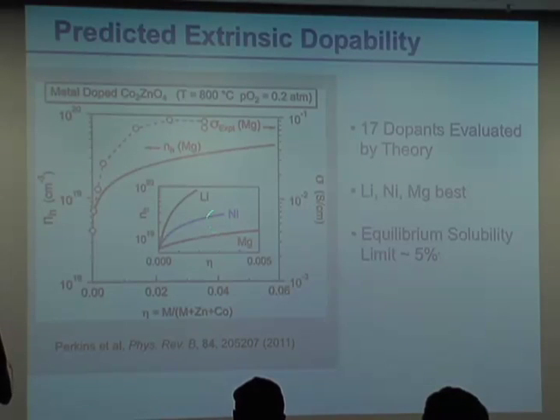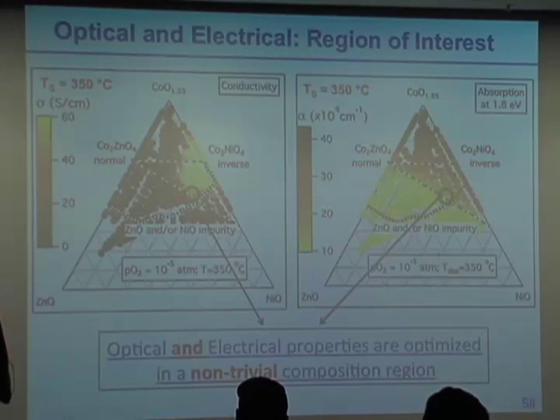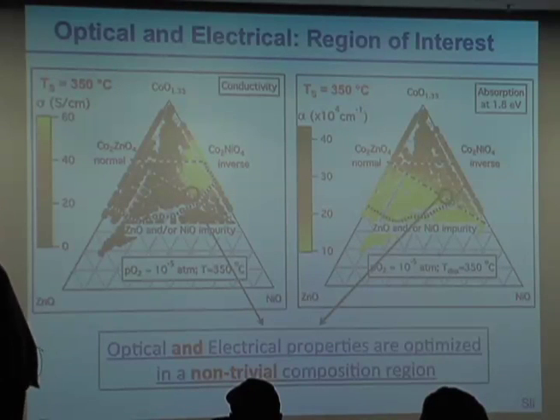And nickel, of course, also makes inverse spinels. And so we looked at, and this is a combinatorial setup where we sputter zinc oxide, cobalt oxide, and nickel oxide. We can make these gradients. Basically, here is the cobalt zinc oxide spinel that's normal. On the far right would be all nickel, and that's the inverse spinel, where nickel is on the octahedral site and cobalt is on both the octahedral and tetrahedral site.